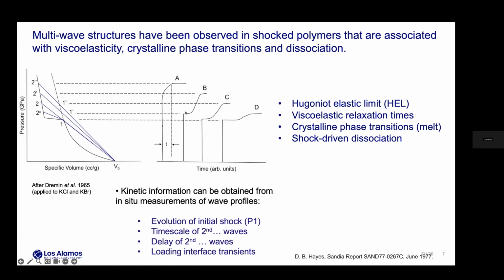So you'll sometimes see evidence of a first wave followed by a second wave that could travel slower than the first wave, or eventually catch the first wave. And then often some of these rounding and second wave features are associated with kinetics of the transition. So I just wanted to put this up here to say that when we look at the shock waves coming from our polymer samples, we have to keep in mind there's a lot going on here, and we can use the shock wave dynamics and carefully design our experiments to get at some of that quantitative information just from the profiles themselves.